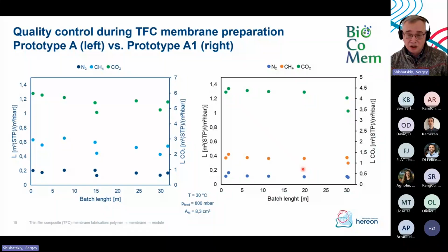So, of course, since we took a lot of samples, we do screening of the membrane quality along the membrane length of this roll, which you have seen before. And here you can see data for nitrogen, methane, and carbon dioxide for two prototypes, A and A1. And you can see that the membrane quality is not changing significantly along the length of the membrane. This is quite nice to know.